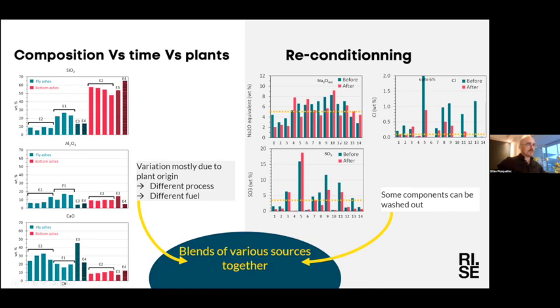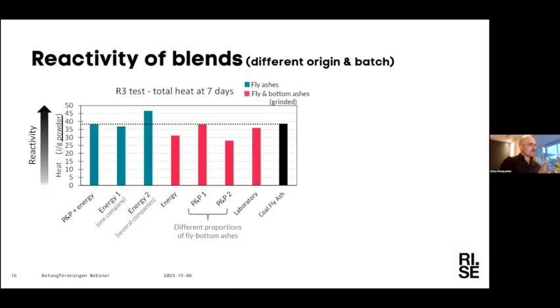But then the idea to follow that, to compensate for those two problems, so if we have too much of the alkali component even after washing, or if we also have too much variation between the different plants, was actually to make blends of different sources to kind of flatten out all those differences. So we made some, not a quick test, but more R3 analysis on different blends. I will go quite quickly there.